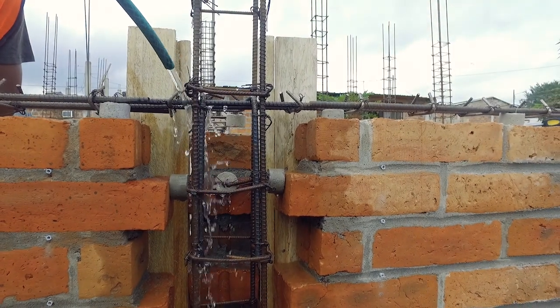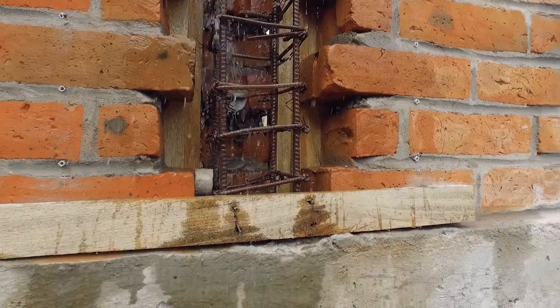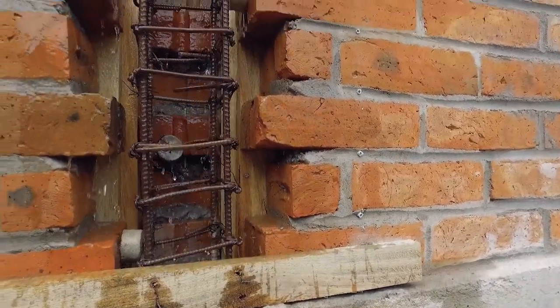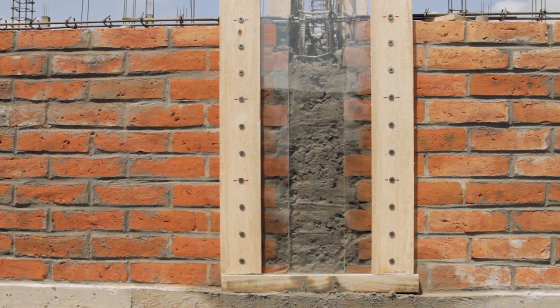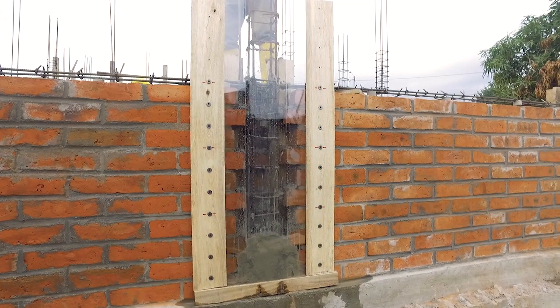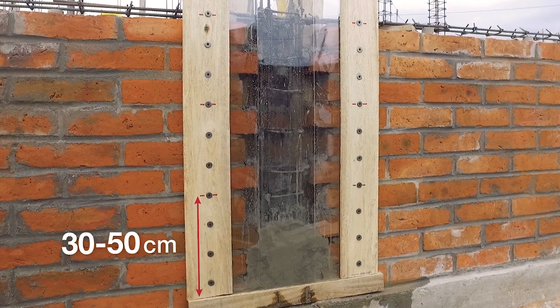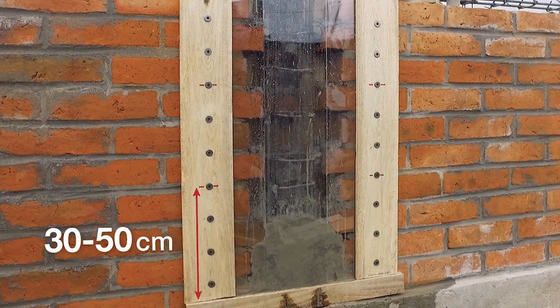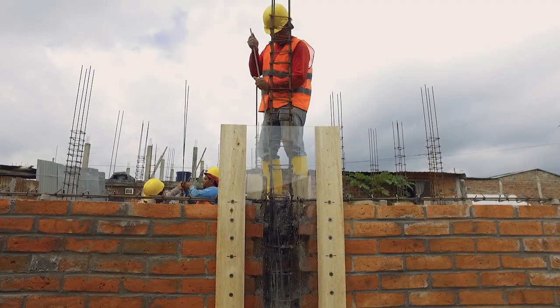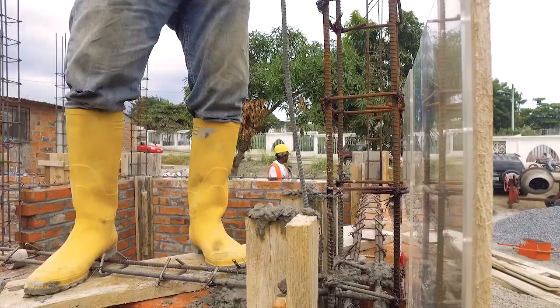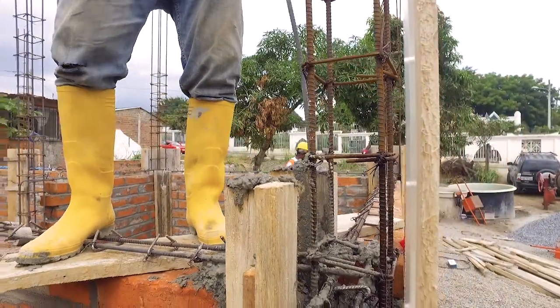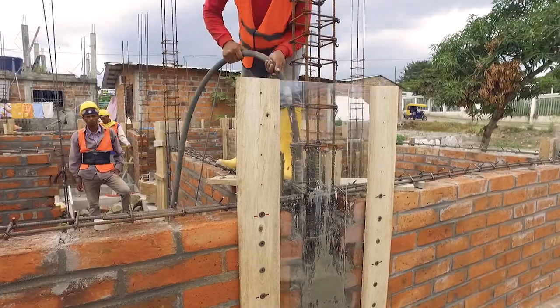Pouring of concrete into the tie columns. The formwork of the tie columns must be wet before pouring, just like for the plinth beam. Don't pour more than 1.20 meters in height of concrete per day. Pour concrete in layers of 30 to 50 centimeters at a time. Compacting should be done after each layer, using a rebar and a hammer or a needle vibrator.